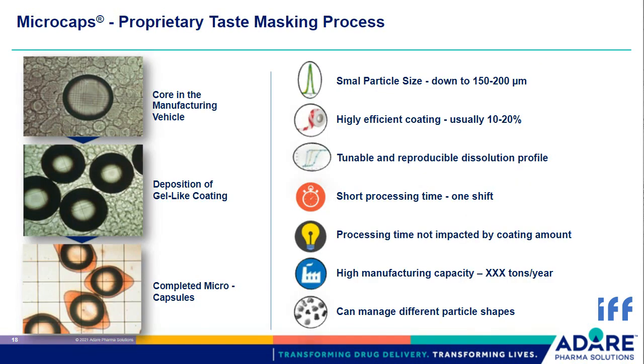Coacervation is a physical phenomenon leveraged for the application of a continuous coating around the particle. Coacervation can be described as the coexistence of three different not mixable phases in the system. On the left side, you can see some pictures representing the sequential steps of the microcaps process. In the first picture on the top, you can see the core particle, representing the first phase, suspended in a liquid vehicle. The liquid vehicle is a solution of the coating polymer.